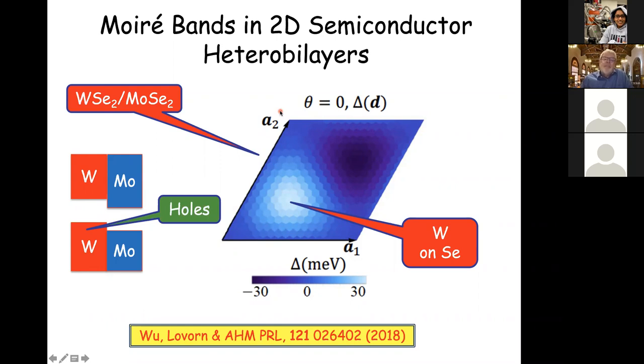And 10 to the 13 per square centimeter is, let's say, a part in 1,000, 1 electron per 1,000 atoms. With gates, you cannot change the chemistry of a two-dimensional crystal very much. Chemistry depends on number of electrons per atom, but you can change the number of electrons per artificial atom by a factor larger than 1. So you can effectively dope, by large amounts, without introducing any disorder or any different atoms, and you can do it all in situ.